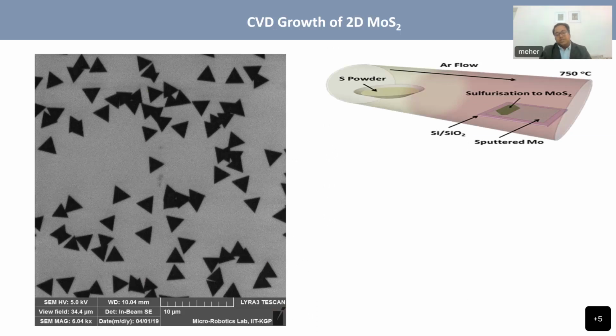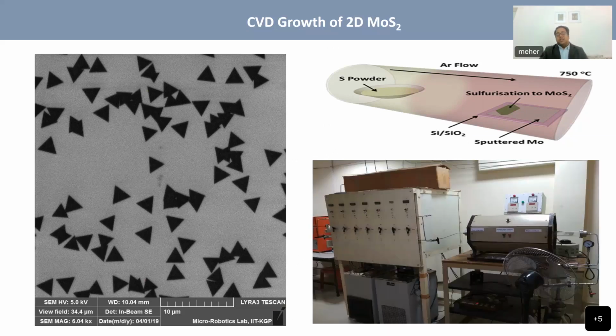Then we tried a different kind of material. I talked about molybdenum sulfide also. These are the molybdenum sulfide flakes, which are prepared by the chemical vapor deposition method. In this method, what happens? We have sulfur powder and we have molybdenum metal deposited on a substrate or silica substrate, and when we evaporate the sulfur powder and have a very high temperature at the molybdenum substrate, it reacts with molybdenum and becomes MoS2. And then there are other variations of such setups also.